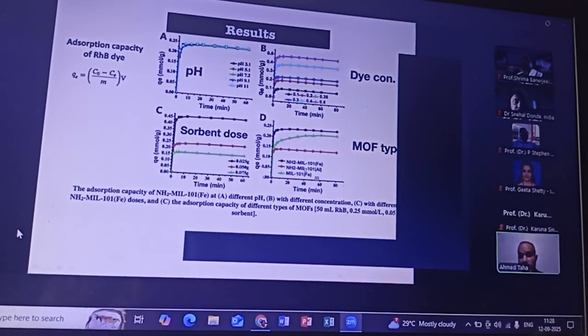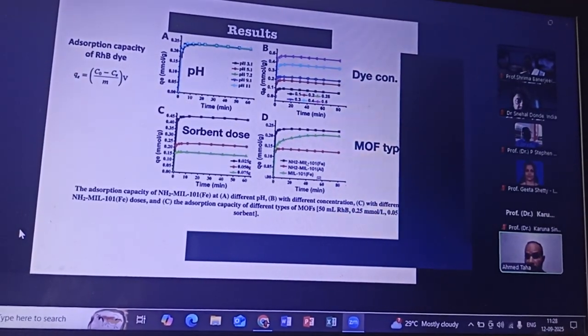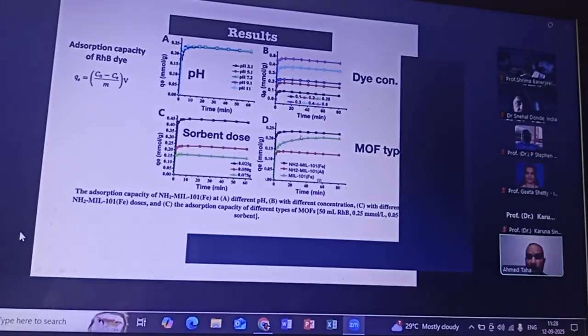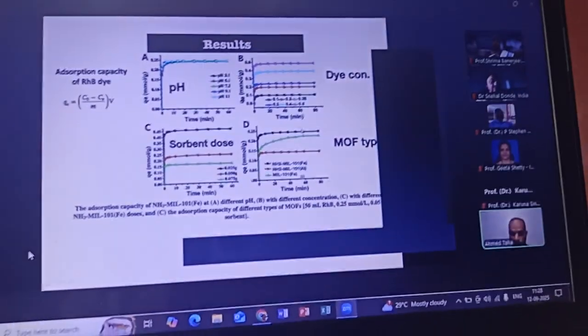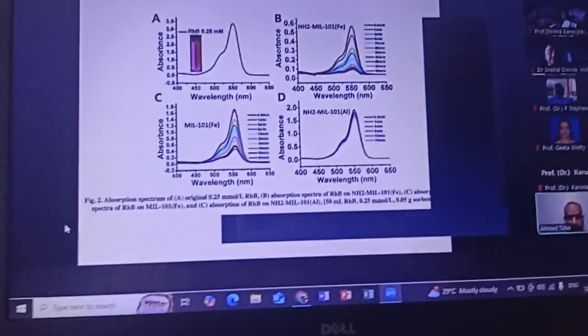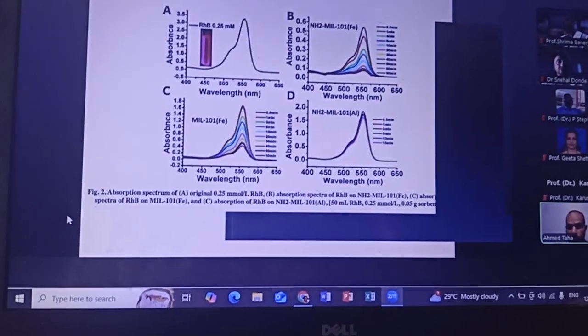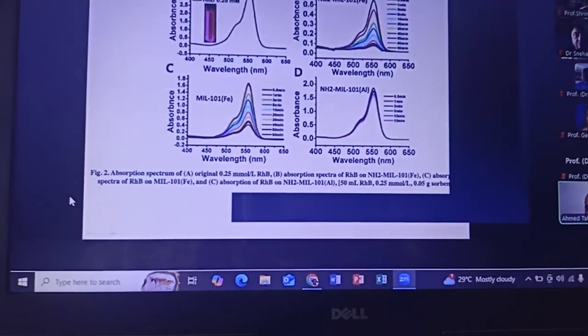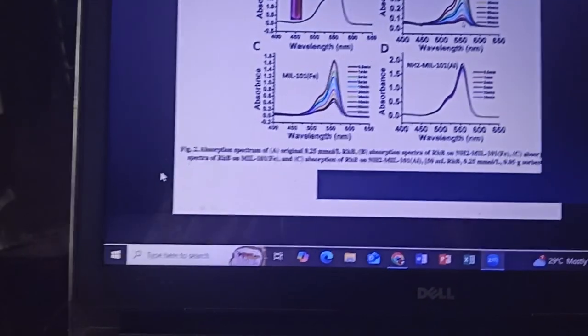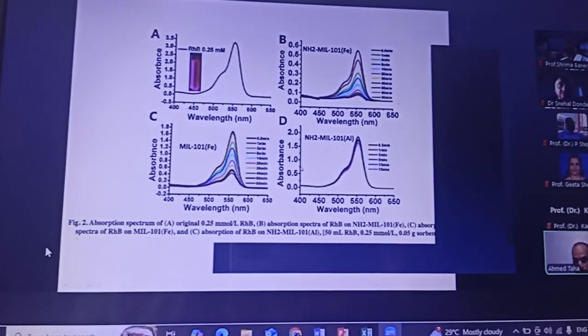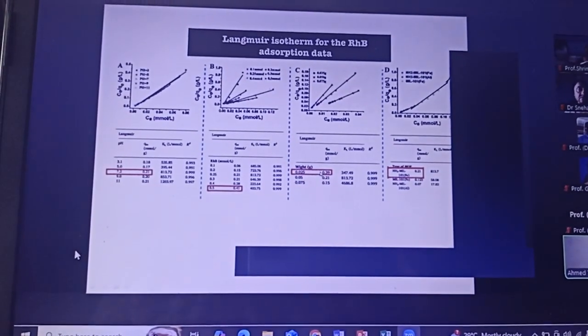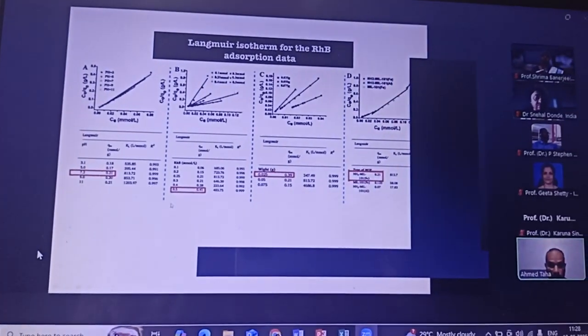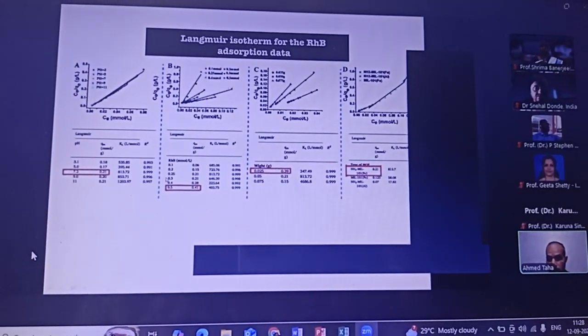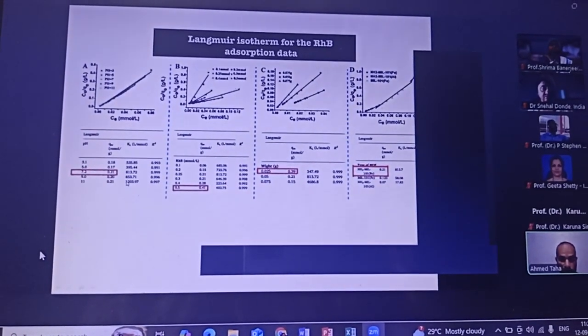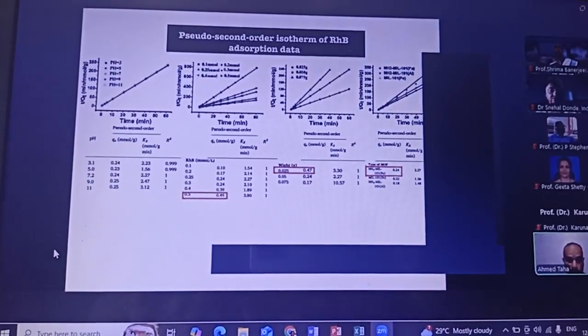We also compared the 3 materials. We found the one with the iron and amine, as we hypothesized, has the highest adsorption performance. And this is a visible performance. You can see the material with the amine group and iron has better adsorption performance compared to the other 2 materials. And here is the performance with numbers. These numbers can tell us which material has better performance in adsorption.